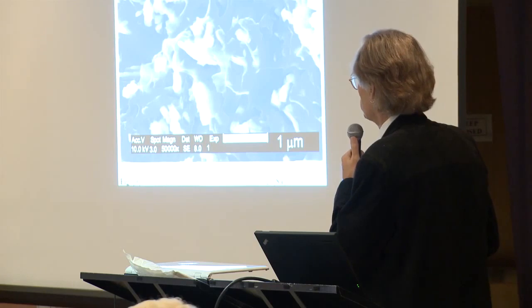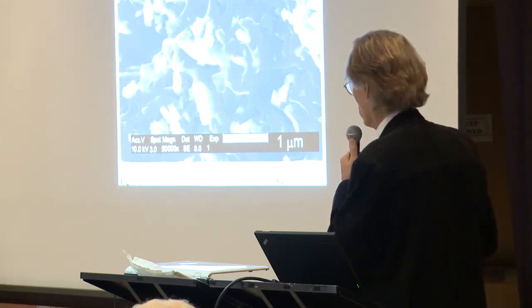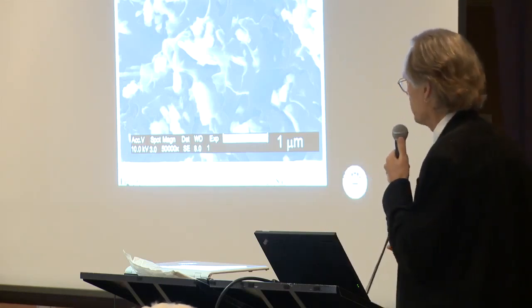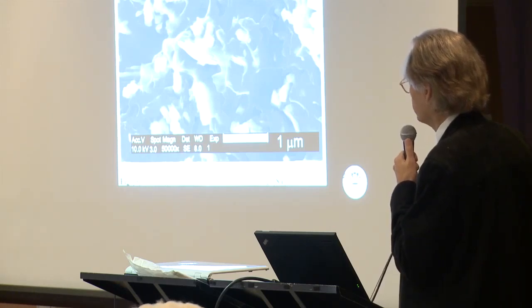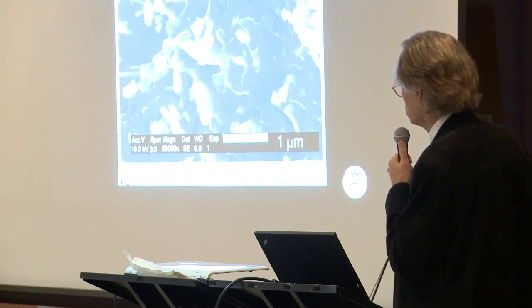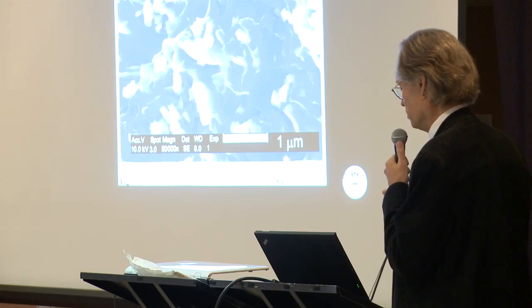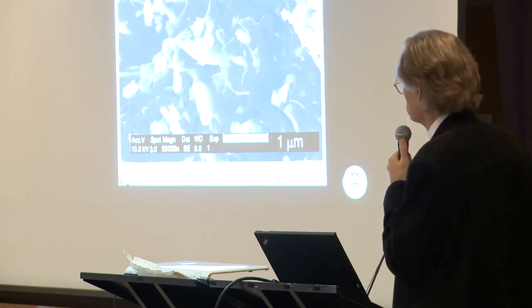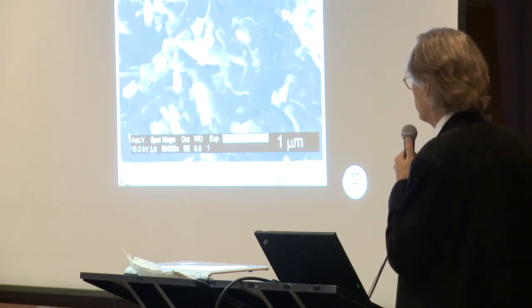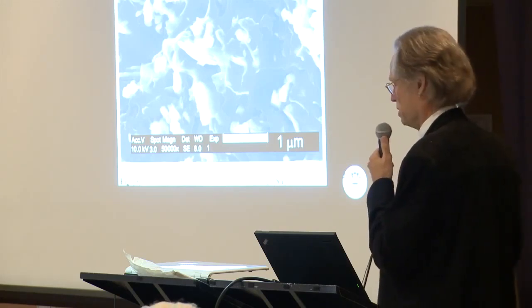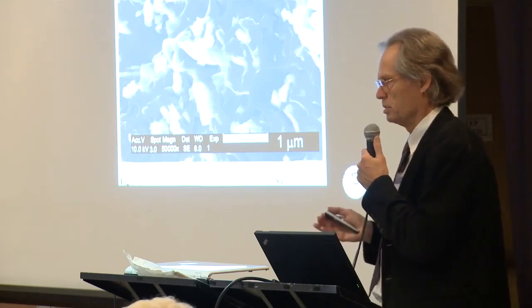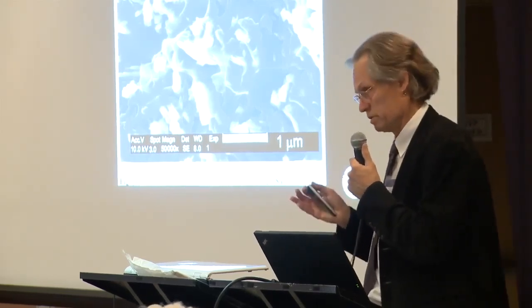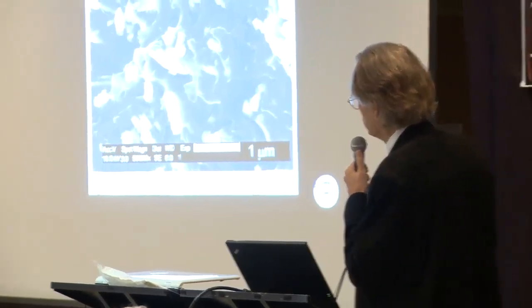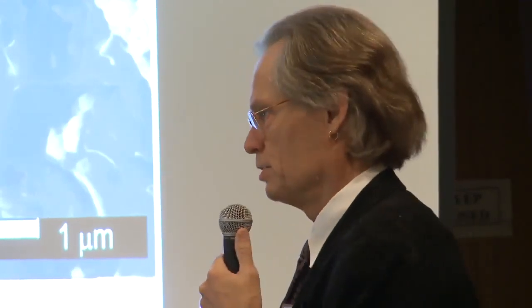This is an even greater magnification, also an electron microscope picture of the red phase, where we can further identify the particles involved. We see some plate-like structures here. We see some smaller, but still crystalline, meaning that they are hard. And apparently some random phase here. And this, I can already say, is the polymer, the plastic, because this material has properties common with paint. Meaning that these particles are embedded in a plastic matrix. I use the word plastic to make it simpler for you. A scientist would say a polymer matrix, but maybe that is too far out.